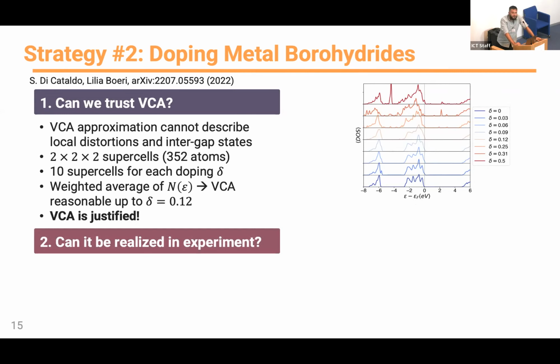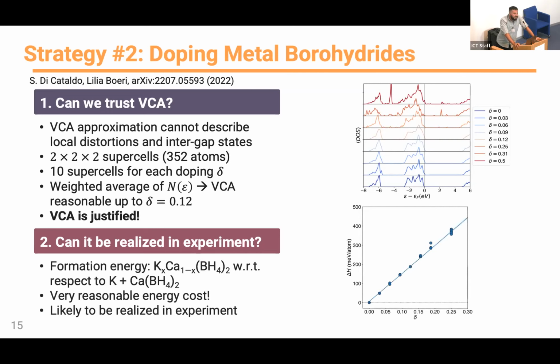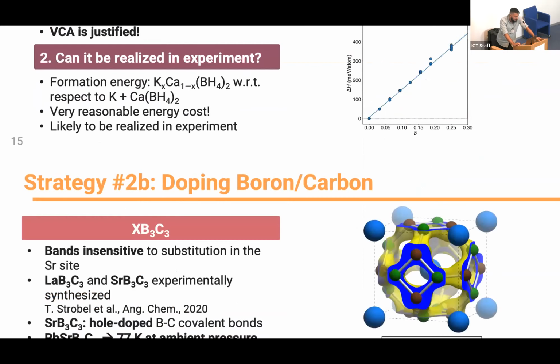Now, can this system then actually be realized in experiment? Since we already constructed the supercells, we could for free obtain the formation energy with respect to doping. And so what you see here is the formation energy of the doped structure with respect to the composition into pure potassium and pure calcium boron hydride. Of course, it costs energy to put doping into the system, but we see that up to dopings of about 10%, the energy cost is absolutely reasonable. We are within a range of 100 meV per atom, which is usually accepted as a reasonable threshold. So yes, this is also likely to be realized in experiment, also considering how easy it is to get your hands on the material itself.